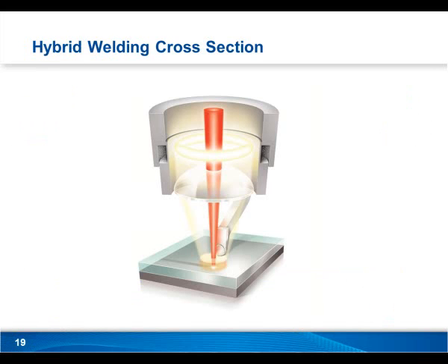So here's a cross-section of the hybrid welding head. Essentially what's happening here is you can see the high-powered halogen lamp, and this is a polychromatic light source. And so as I mentioned earlier, the laser, being monochromatic, is going to pass directly through this upper transmissive layer, and it's going to absorb all of its heat into the lower layer. So the only way that the upper layer is going to be able to get heat from the laser energy is through conduction between the two pieces of plastic. Now this is great, and it works for most laser plastic welding applications, and it will work for taillights.